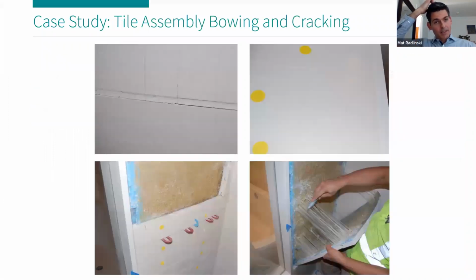Next slide. Here's an example of an unfortunate physical interaction between polymers and cementitious materials in tile installation. And this unfortunately affected literally hundreds and hundreds of bathrooms, obviously in a commercial setting. In this particular case, the tile assembly consisted of ceramic tile, a fairly thick layer of tile thin-set mortar installed on top of a sheet waterproofing membrane, adhered, as you can see, with an adhesive to an underlying gypsum backer board.